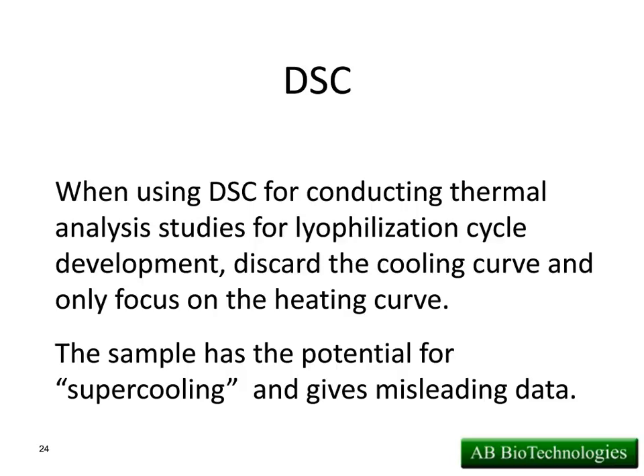Now, is it applicable to what you could do in a freeze dryer? No. But what we found is that sometimes we get samples from people that have put things in there that are just horrendous. So we don't even get the sample frozen until negative 50 or 60. So we don't want to miss anything. So, through experience, bad experience, we've learned to just go down as low as we can go, and then we warm up from negative 90 to room temperature just because we don't want to miss anything. You know, being a contract development lab, we see all kinds of stuff under the sun. So now we generally go down to negative 90.